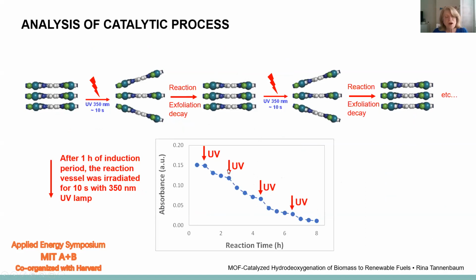And then again, after 2 hours, we do that again. We irradiate for 10 seconds, and then again and again. And so basically what we're doing is we're opening and closing the layers during the reaction. And then what we note is that we have these steps that correspond to the time where we have the irradiation. And then the rate of reaction actually changes as we irradiate.